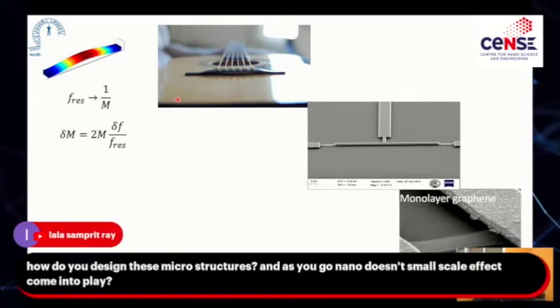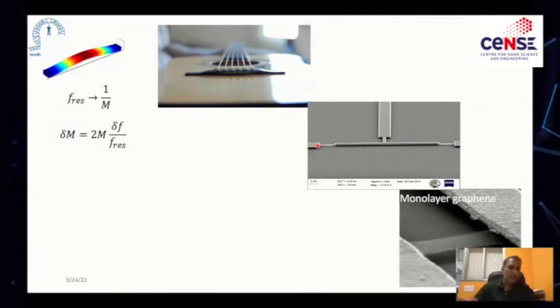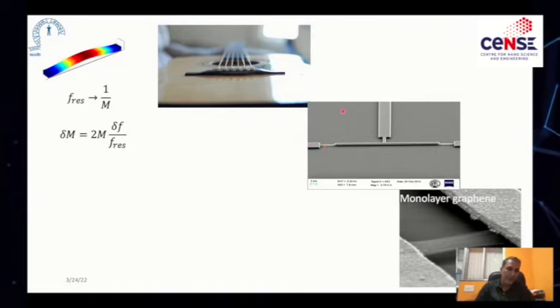All right. So for example, this, right? Let's say, how do you design this? What you do is you start with a wafer, for example. Exactly where you want the string to be, you cover it with certain material so that it protects everything underneath it. So we will put some material right here so that it protects it. And then you use some ions to bombard. Everywhere the material is protected, nothing happens. Everywhere else, the material is removed. That's a process called etching.